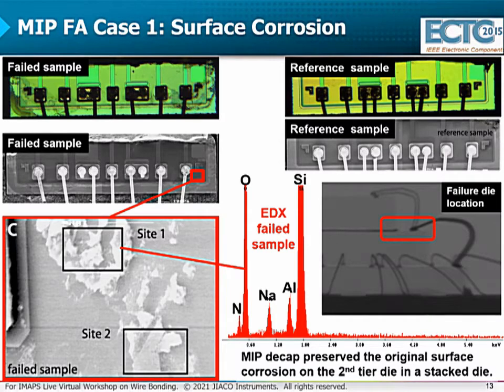Let's discuss results. After MIP oxygen-only decapsulation was applied to both of these samples, the reference sample showed no apparent abnormalities on the second die, and EDX at several locations, also on the surface of the second die, showed that there was no contamination present.